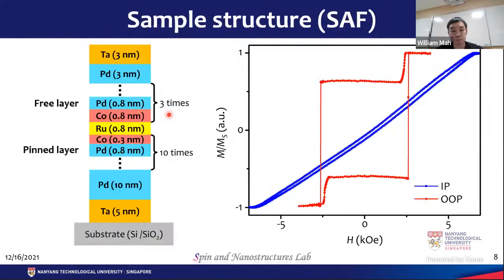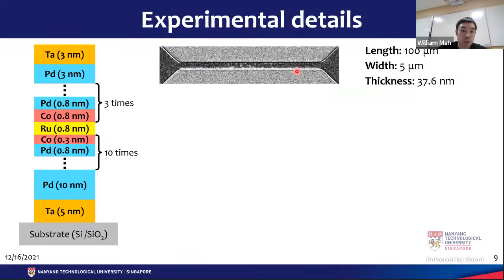Let's see the experiments. I utilize a cobalt palladium multi-layer sample. If you look at this red color hysteresis loop on the right here, this corresponds to the out of plane hysteresis loop. You can tell that this cobalt palladium multi-layer sample has synthetic antiferromagnetic properties. Using optical lithography, I fabricated a microwire of length 100 micrometer, width of 5 micrometer. The thickness is just the thickness of the entire sample minus the substrate.